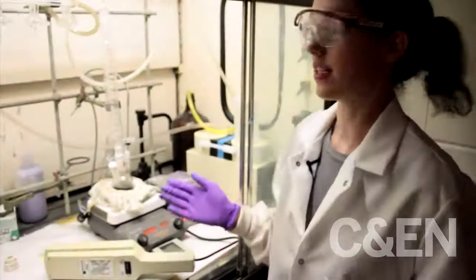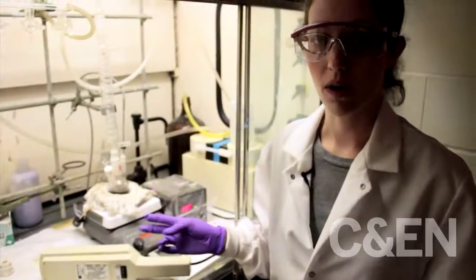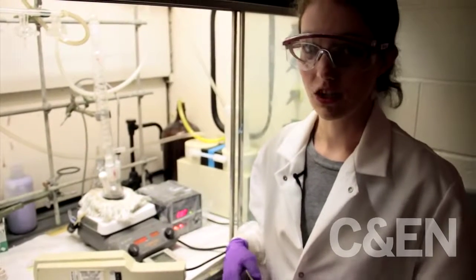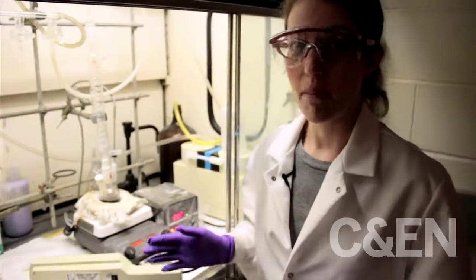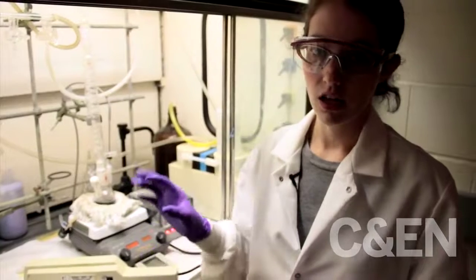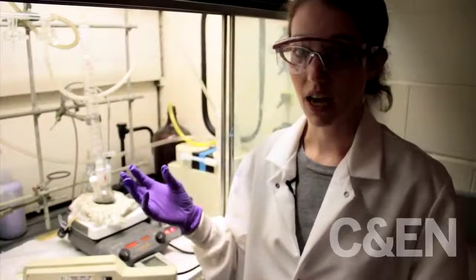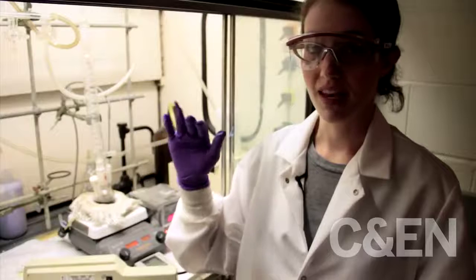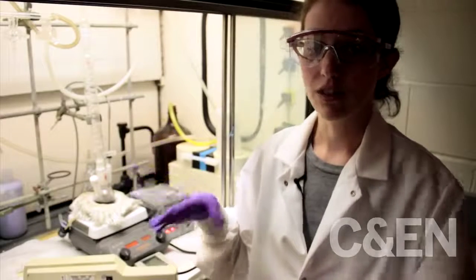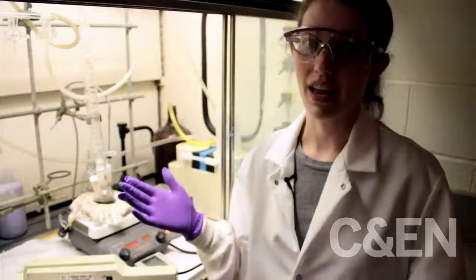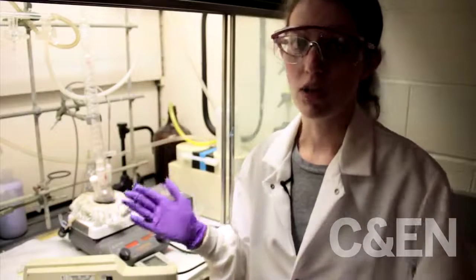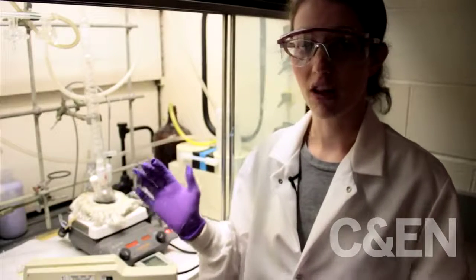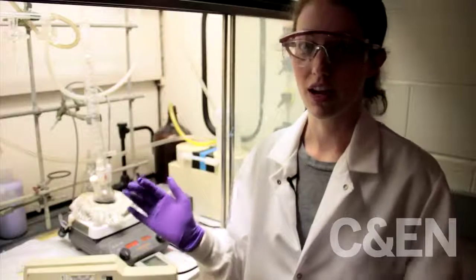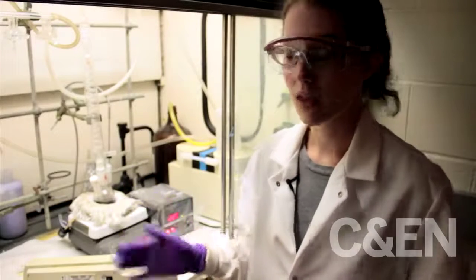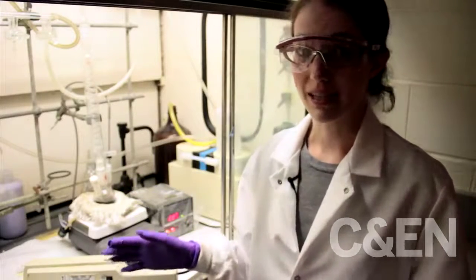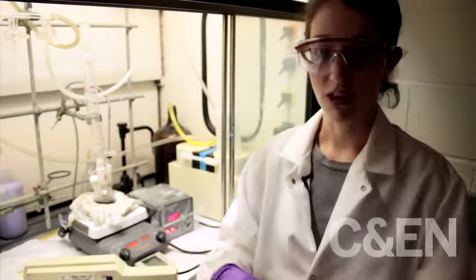So after this process is over, we have what we call the quantum dot cores. And this is essentially the quantum dot, but it's imperfect. The shell, or the exterior of the quantum dot, is not very smooth. And those imperfections mean that it doesn't glow as bright as it potentially can. So we do another process where we put a shell around that to help smooth those imperfections and get very bright quantum dots. And after that whole process is complete, we end up with the finished product.